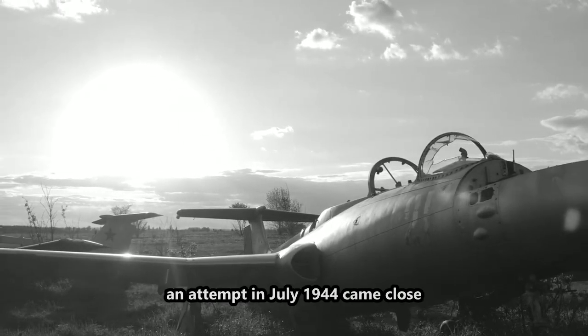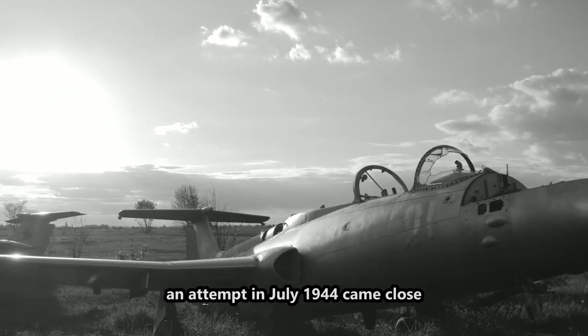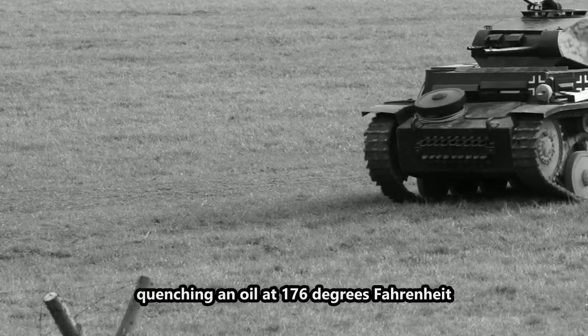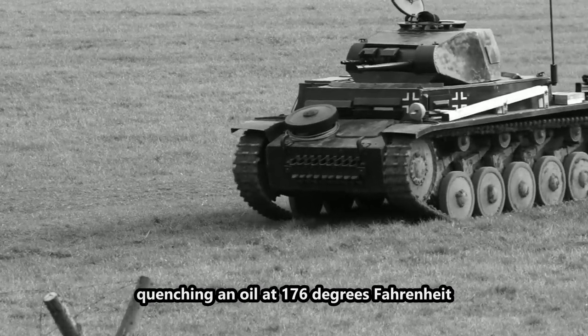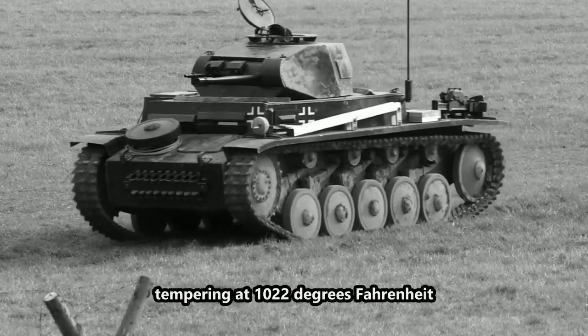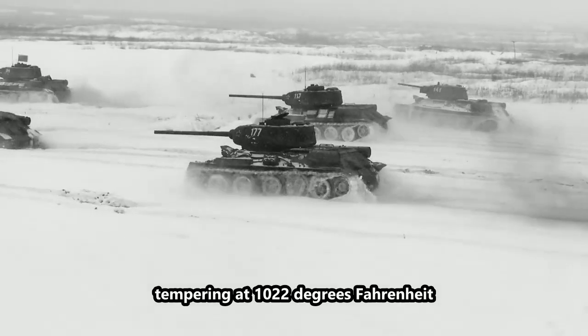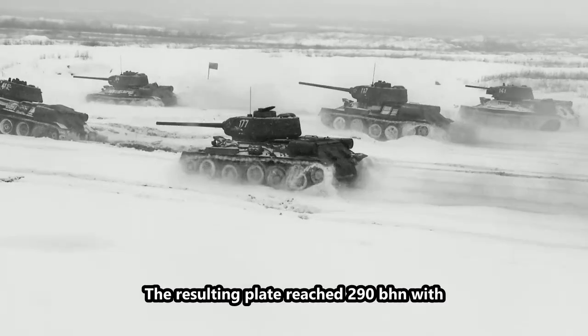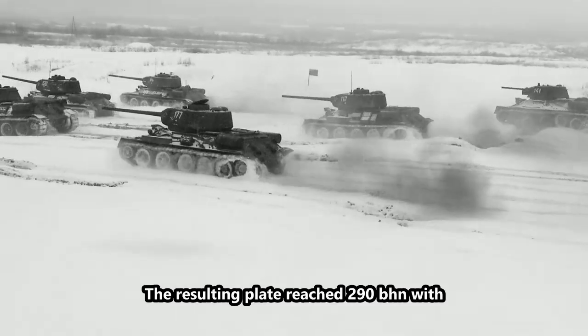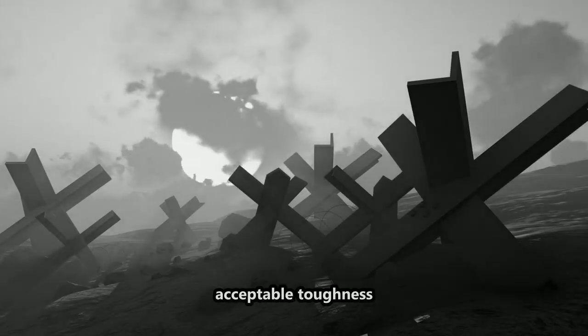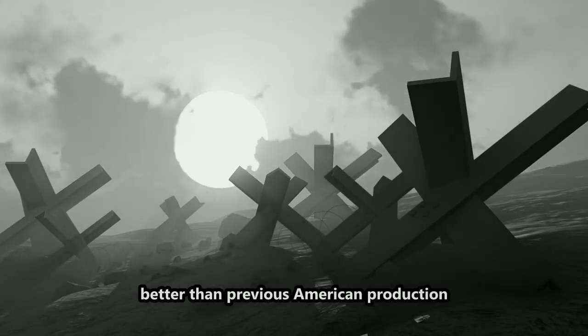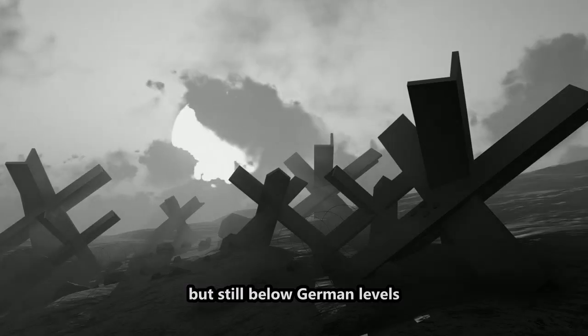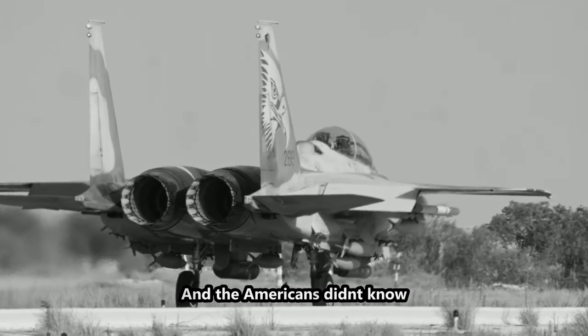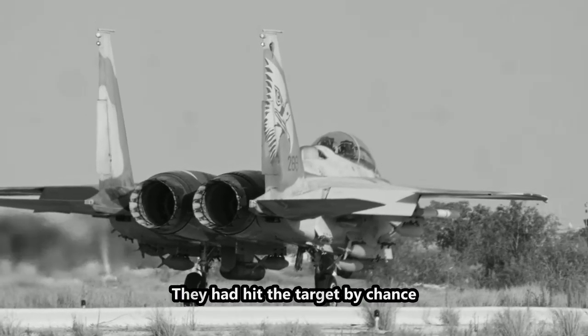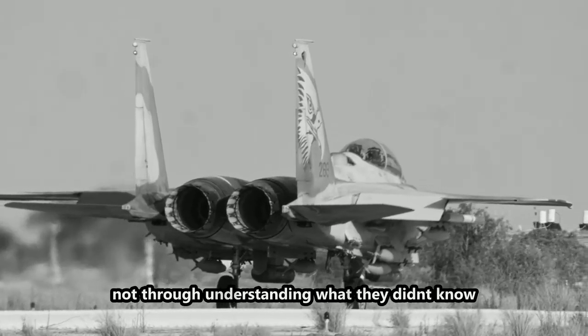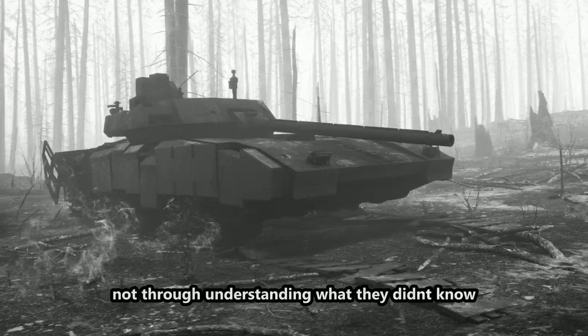Most failed. An attempt in July 1944 came close, quenching in oil at 176 degrees Fahrenheit, followed by double tempering at 1022 degrees Fahrenheit. The resulting plate reached 290 BHN with acceptable toughness, better than previous American production, but still below German levels. And the Americans didn't know why. They had hit the target by chance, not through understanding.